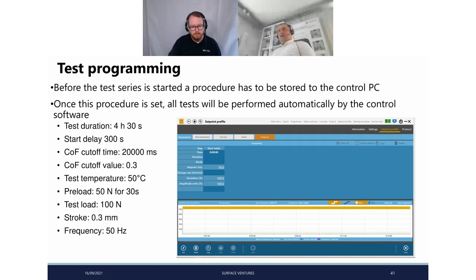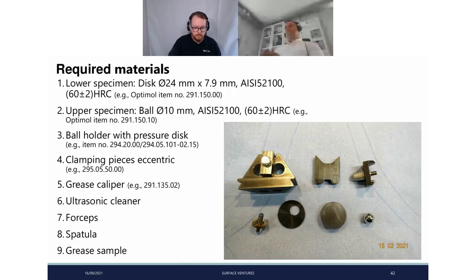The parameters for the fretting standard method are displayed here. You can find them in literature as well and in the records of this webinar. The materials we are using for the test, in the standard method and in the demo, are a steel ball, on the right bottom, against a steel disc, which is the second from the right in the lower line. And for applying the grease, we have a grease caliper which applies a well-defined amount of grease. And then we have the clamping pieces and the sample holders. You will see how we install them into the test chamber.